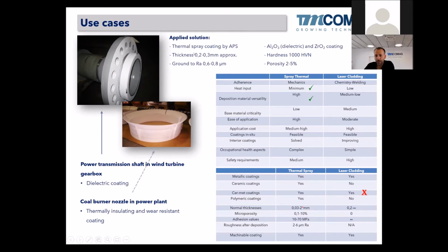So the applied solution, thermal spray coating in both cases by APS, by plasma. As we have to apply a ceramic, we have to use plasma spraying because of its higher melting temperature. It has a more powerful flame, so it's able to melt the high melting point ceramics during the process. So we use the plasma here, atmospheric plasma spray. The thickness of the coating is approximately 0.2 to 0.3 millimeters. And then in this case, it is going to be ground. In this case, we are going to leave it as sprayed because there's no need for precise dimensions in this burner.